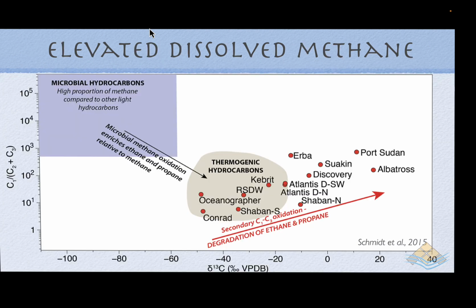It's also interesting if we look at, as we mentioned earlier, the carbon-13 values and also the ratio of the lightest hydrocarbon, methane, to slightly heavier hydrocarbons, the C2, C3 range. We're not looking purely at microbial signatures in the methane dissolved in these brine pools. That's the purple shaded area. We're looking at conditions with carbon-13 values much more indicative of thermogenic hydrocarbons. These are thermal maturation derived hydrocarbons, not the products of biochemical methanogenesis.